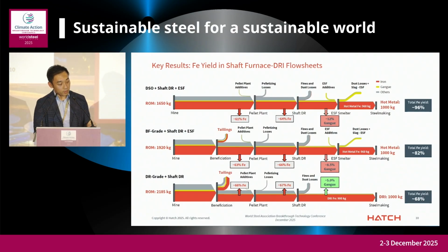I think the biggest difference you see there is the total iron yield compared to where you start, which is a run of mine. The yield difference is quite significant. Roughly a 2% increase in the iron in the pellet is about 14% yield loss across the entire value chain, starting with the run of mine. So getting to approximate commercial DR-grade iron ore is almost 30% iron yield loss compared to unbeneficiated DSO-grade Pilbara iron ore. So I think we can be quite confident saying that not beneficiating at all is probably the best option. Again, you try to avoid beneficiation if you really want to preserve the best advantage of DSO iron ore, which is efficiency in being able to use it.